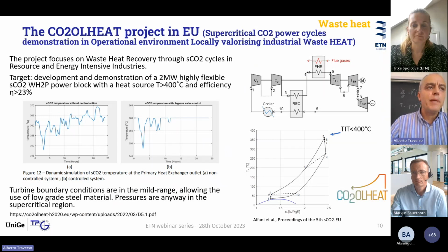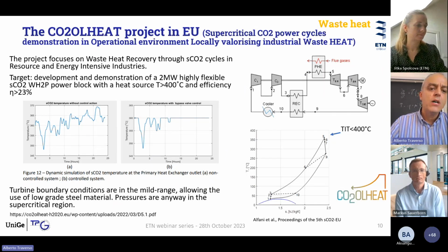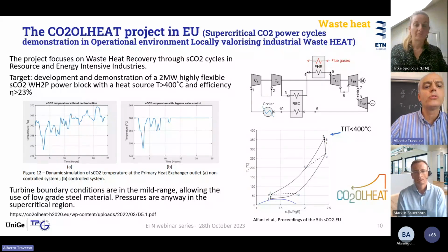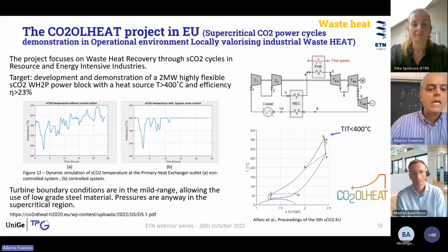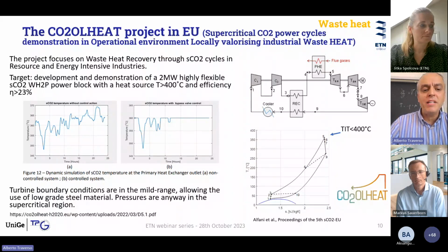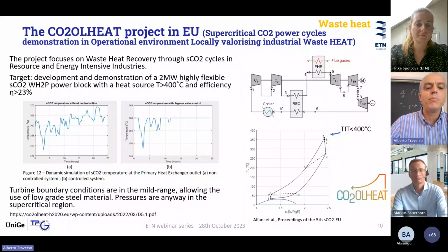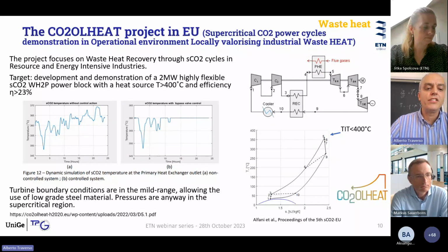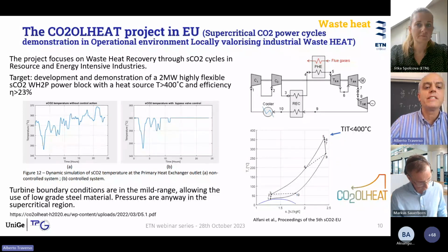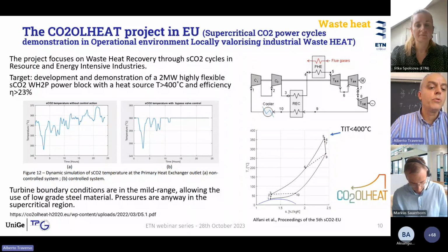If instead of CSP plant, we go to projects that actually are targeting a different perspective, so waste heat recovery, we see that the boundary condition for the expander goes to less demanding conditions. And in particular, if we mention, for instance, the CO2OLHEAT project, we see here that from the public simulation published by them, there are significant transients in inlet temperature, but more or less it's always below 400 degrees C. So the plant in this case is still handling a pressure in the supercritical region, but the temperatures are much milder. This means that for the turbine, low-grade steel material can be used.